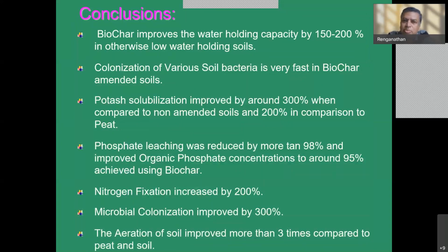Conclusions. Biochar improves the water holding capacity by 150 to 200%. Colonization of various soil bacteria is very fast in biochar-amended soils. Potash solubilization increases by around 300%. Phosphate leaching was reduced by more than 98%. This phosphate leaching is what is causing a lot of problems for our water bodies. So by adding biochar, you're going to limit them from going into our water bodies, and it will be more useful for the plants.